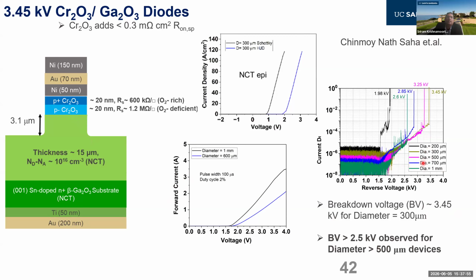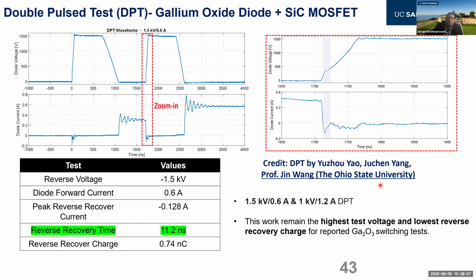kV. And so once we made these 1 amp, 3 kV diodes, we collaborated with the Ohio State University, Professor Jin Wang's group, to do double pulse measurements in these diodes. And then estimated or calculated the reverse recovery time in these diodes, which was presented at APEC, the Applied Power Electronics Conference, a few months ago. And so here we can get extremely impressive reverse recovery times in these diodes.